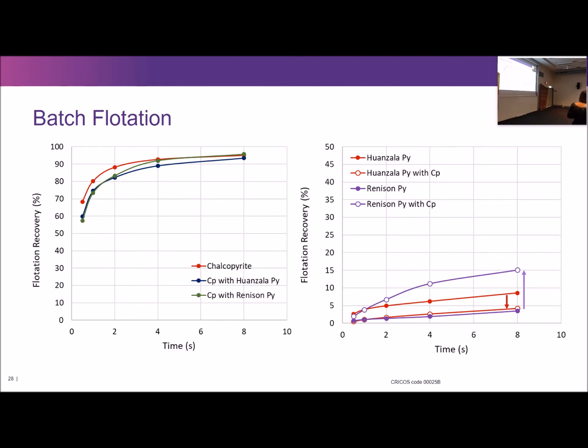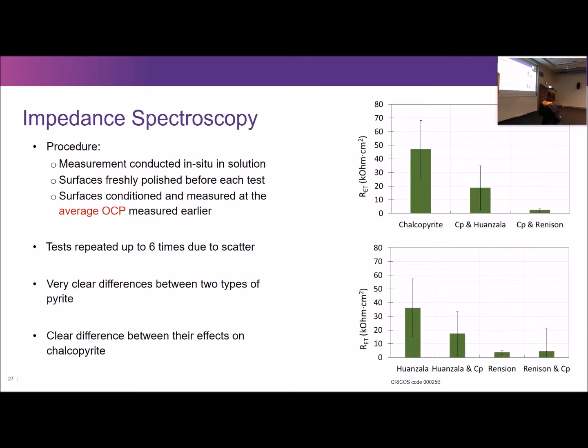On the other hand, Renison pyrite hardly floated at all on its own. But when mixed with chalcopyrite, floatability shot up. And even without proper reproducibility of error bars, you can see that that's real. But I wouldn't try and quantify it in any meaningful way because of no error bars. And so here, I was expecting it to go up. The error was too big to say with certainty, but I would guess that if I was going to go back to do more repeats, I would likely see that going up more.